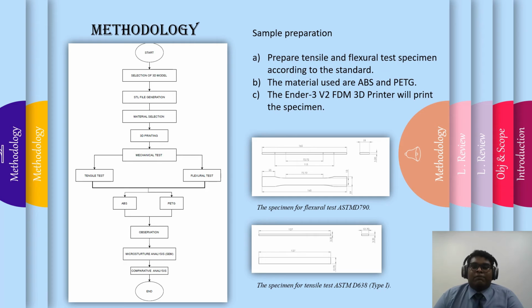Moving on to sample preparation, the specimens are prepared for the tensile and flexural tests according to the standard. The materials used are ABS and PETG, as mentioned before. The specimens for flexural tests are according to ASTM D790. The specimens for tensile tests are according to ASTM D638 Type 1.